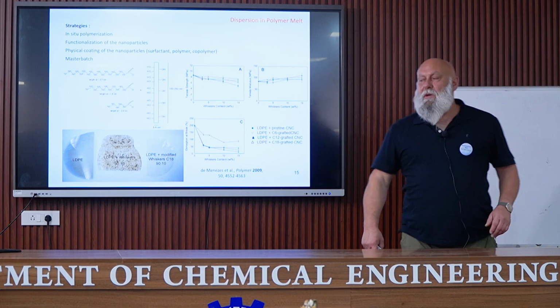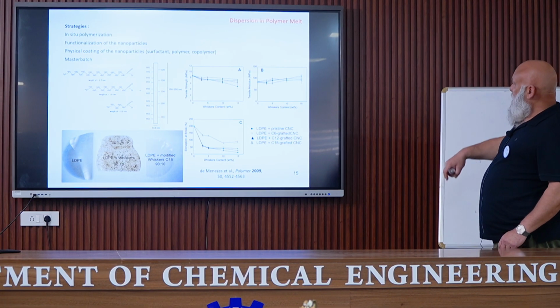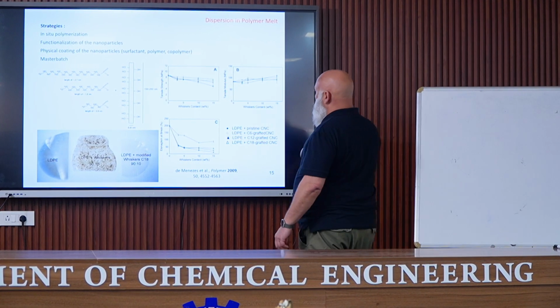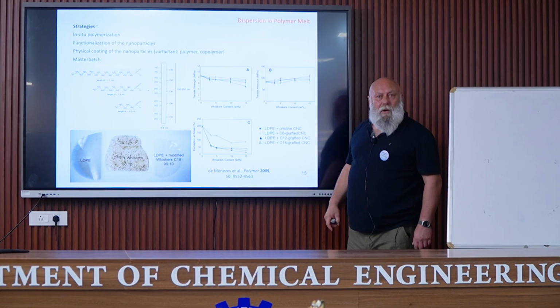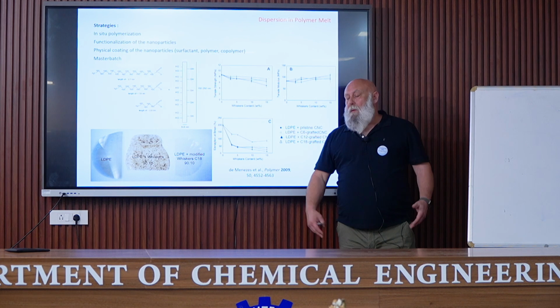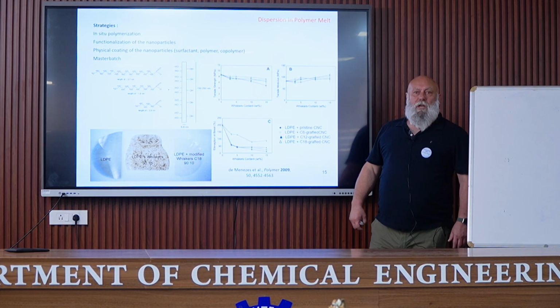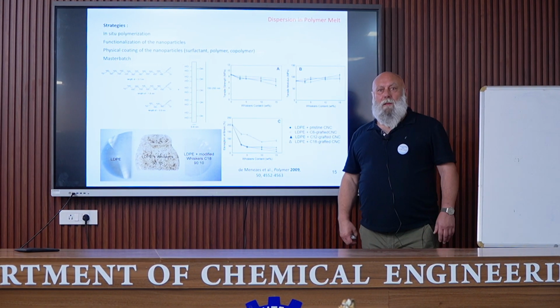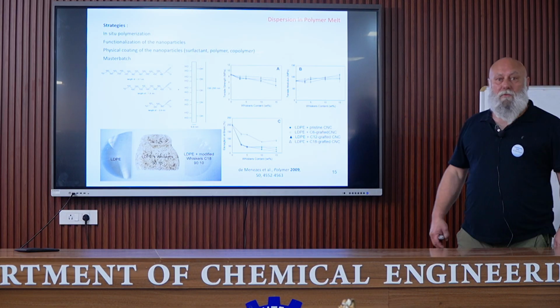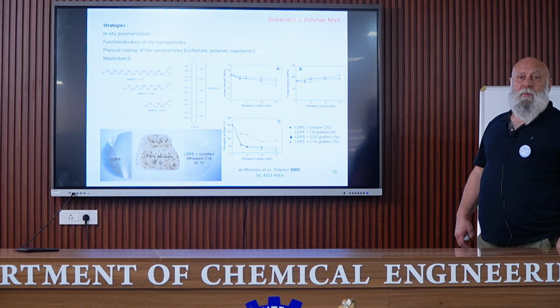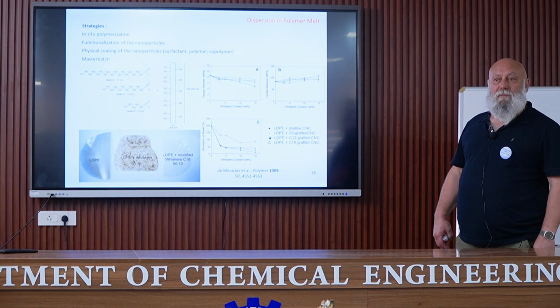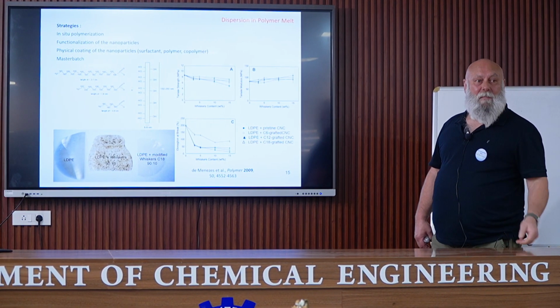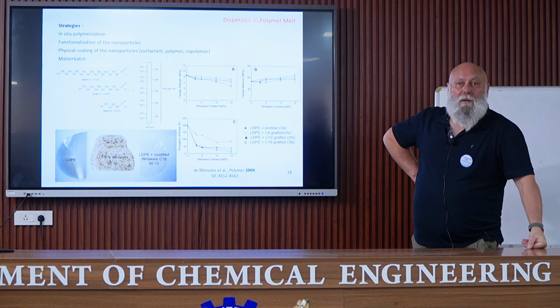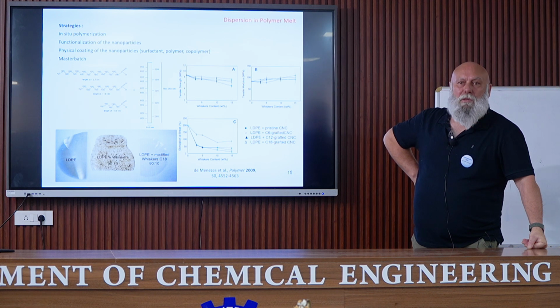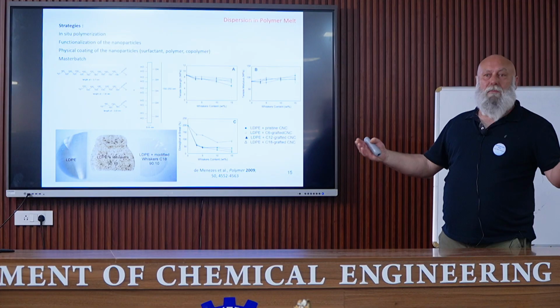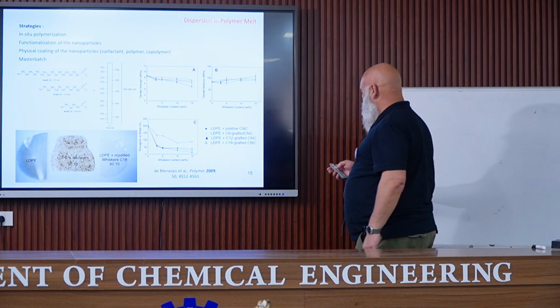Now, what about the mechanical properties? You have here the tensile strength, modulus, elongation at break, as a function of CNC content for the different samples, with and without modification, except here, for this curve, there is no change. We have a better dispersion of the nanocrystals in polyethylene after modification, of course, but no improvement in the mechanical properties. What is the reason for this? Do we have any idea? We block the OH groups. The formation of the percolating network is no more possible, meaning that even if the dispersion is improved, there is no improvement in the mechanical properties.